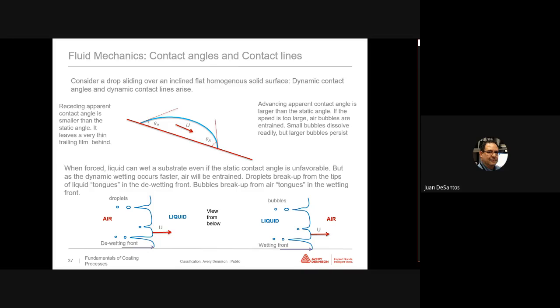Now let's see what is going on there in those fronts of wetting and dewetting. Now, in the dewetting front that occurs in the back of the droplet, if the speed is large enough, the liquid will leave trails that break into droplets, which you may have witnessed on shower walls as water droplets slide down. In the wetting front here, if the speed is large enough, air invades the liquid, and these air tongues then break into bubbles in the liquid. Smaller bubbles will dissolve readily, but larger bubbles will persist. In summary, when forced, a liquid can wet a substrate, even if the static contact angle is unfavorable. But as the dynamic wetting occurs at faster rates, air will be entrained.